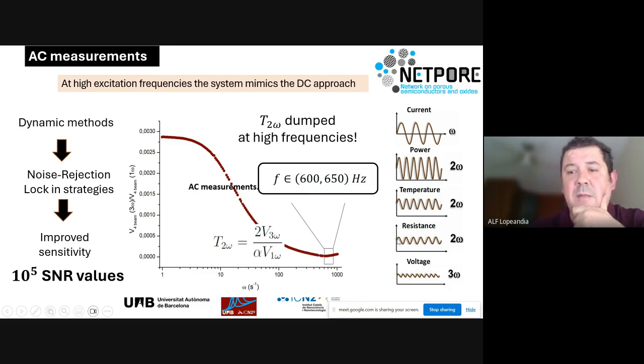The temperature oscillation, of course, can also be seen in the resistance. And here we have the DC component plus the 2 omega component, and exactly the same with the voltage. That makes a 3 omega component appear, that is essentially the link between the current at 1 omega plus the resistance at 2 omega. We can minimize the 3 omega component if we play well with the thermal transient of the device. The thermal transient of the device, in that case, was around 20 hertz. And we typically do the measurements at 600 hertz. It essentially means that this 3 omega is right here. This 3 omega voltage is almost negligible.